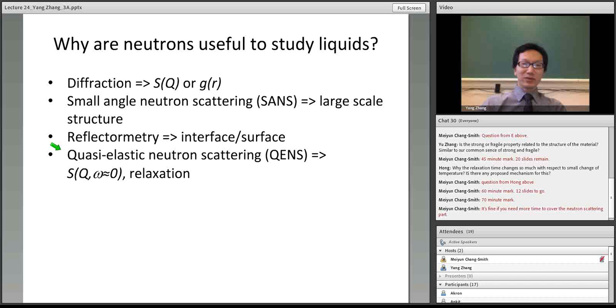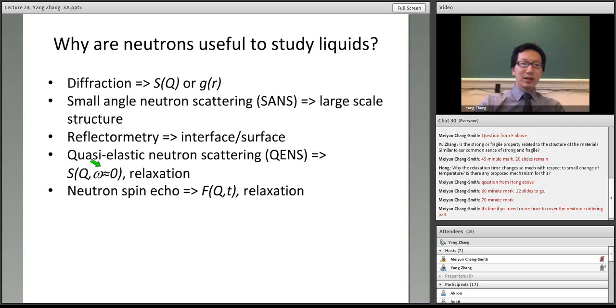For example, if you use thermal or cold neutrons, the energy of the neutrons is in milli-electron volts, and the fundamental excitation of the material is also in the range of milli-electron volts. But for X-rays, we have to use keV X-rays, so we need an ultra high resolution X-ray to do the measurement. By doing quasi-elastic neutron scattering, we basically detect the very small energy transfer near the elastic line, corresponding to slow relaxation. And we can use neutron spin echo and detect the intermediate scattering function directly.